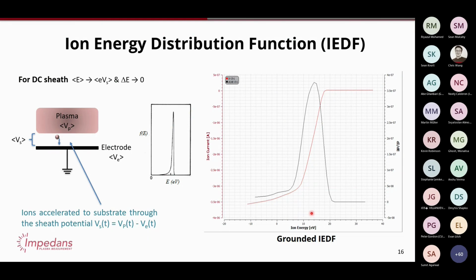Or a more extreme example is if you want to etch through a dielectric material, and it's a very, very hard material, you're going to need super high ion energies. But of course, the way you achieve that is not by just having a grounded electrode. You have to put a bias on it. So imagine if instead of this being grounded, you have some DC bias, minus 20, minus 30, minus 40. Then the resulting ion energies will be the plasma potential plus that bias. So it might be 20 plus another 30, so your ions will get 50 eV. And it'll still be a single peak.